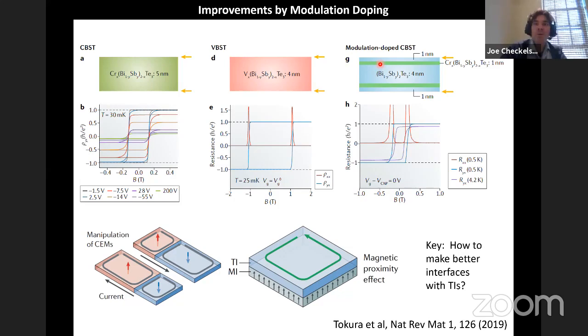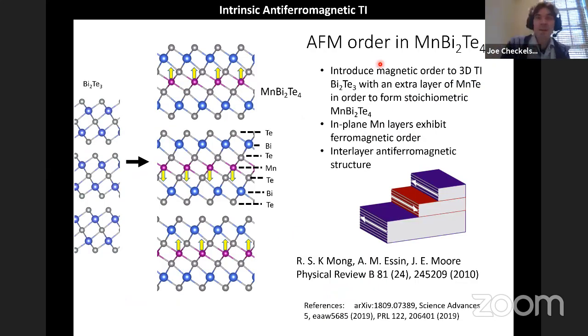So this is the reason I was so excited to answer that question, it segues into this other approach to the problem, which is just finding kind of natural materials which can try to intermingle those two types of layers. And that is, I think, one way of viewing this manganese bismuth telluride. So there's actually many variants of this compound, depending exactly how you layer them together. This is the so-called 1-2-4 variation, where you can really imagine just taking bismuth telluride, so these 5 layers of tellurium bismuth, and inserting a layer of manganese telluride. And this manganese telluride, at least within this one layer, is ferromagnetic.